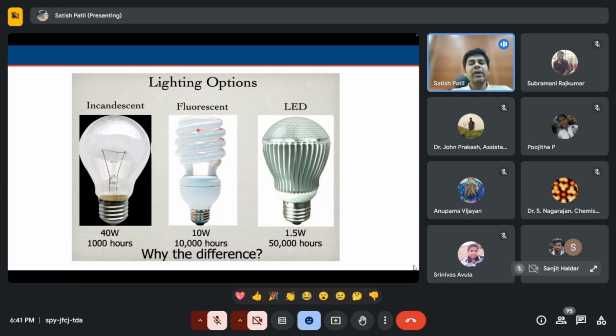So people are trying to replace these. Most of the light we see today is based on fluorescent, but they are also not environmentally friendly. In terms of energy efficiency, they are much better than the incandescent lamp, but however, they are not very environmentally friendly. So eventually people are now trying to do a transition to LEDs, where you use very little power, 1.5 watt, and you can run these LEDs for a prolonged period of time, 50,000 hours.